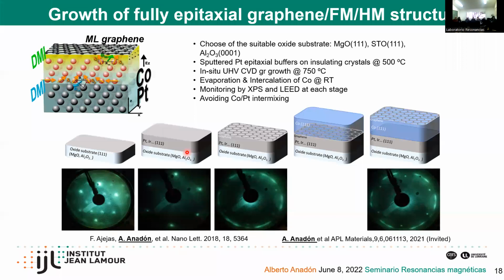Okay, then as you can see, we still have a clean surface by observing the LEED images. These arcs here are related to how graphene grows on top of our material. Basically, we have some rotational domains that are due to some defects in the graphene. And then we can take this sample and grow, using molecular beam epitaxy, a thin film of cobalt on top of it. Now we lose our clean surface, because most things that you try to grow on graphene tend to grow in islands, because graphene is very surfactant. So things tend to accumulate.